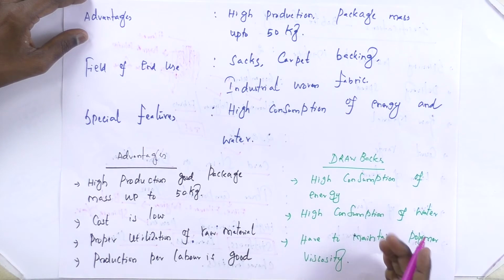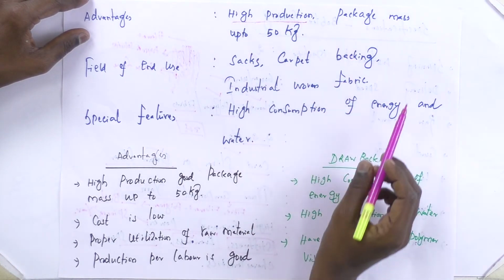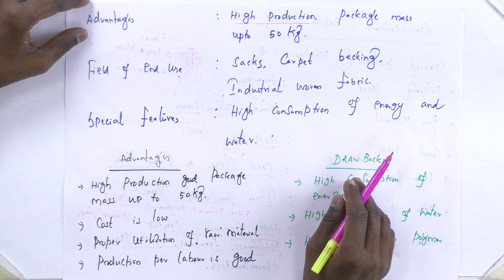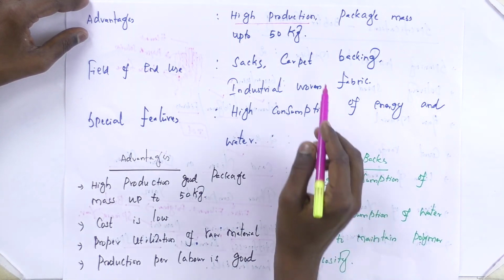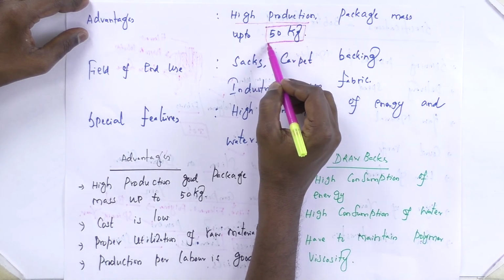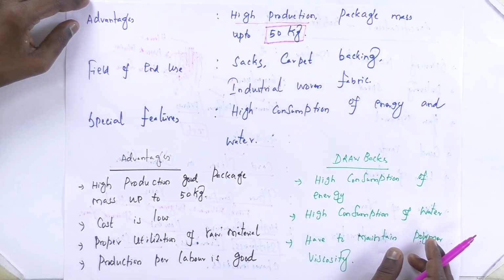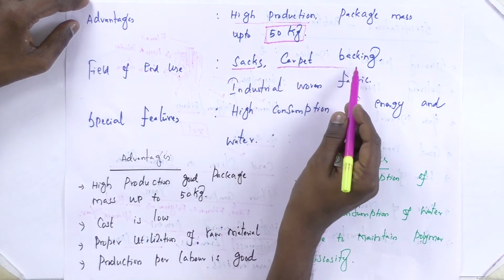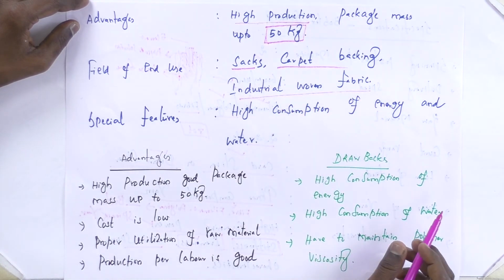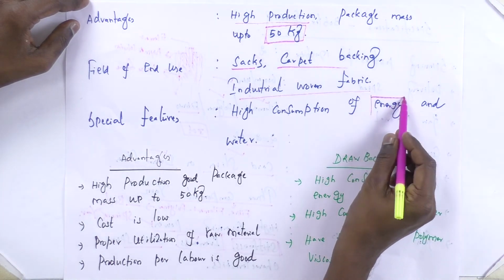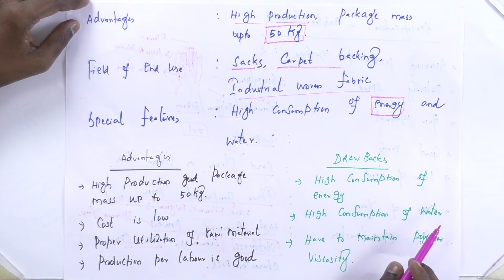So advantages here: high production is possible. The delivery speed is 600 meters per minute, so it is possible to produce more, and the package mass is up to 50 kg. Normally in rotor spinning, air jet spinning and other spinning systems, the package size is around maximum 2 kgs. Here up to 50 kg package weight is possible. Field of end use: sacks, carpet backing and industrial woven fabric. These are all the main fields of end use. And high consumption of energy and water is required for the Bobtex spinning system.